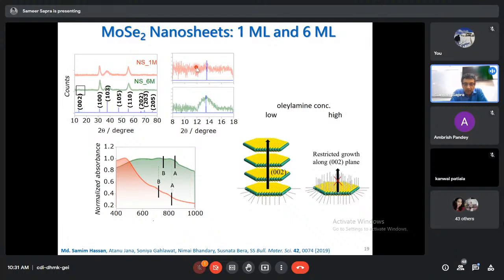And this is a collection of 20 scans, an average of 20 scans in this short, narrow region. For six monolayers, you start to observe some peak. Even six monolayers is very low for diffraction, by the way. And of course, you can look at the absorption spectrum with the excitonic features marked as A and B. They're known as A and B excitonic features in the 2D transition metal dichalcogenide community.